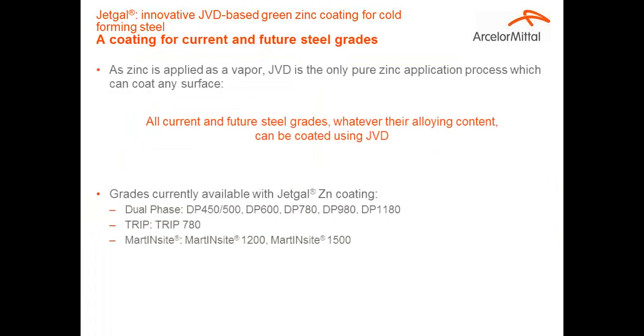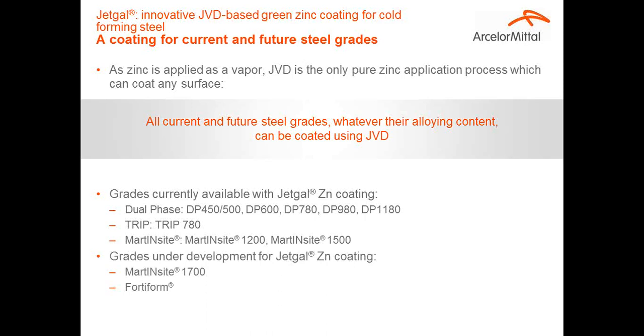So we have decided to use this process for the current HSS and UHSS grades, the ones more sensitive to hydrogen content, and for the future grades, the ones under development. The grades currently available with Jetgal coating are all the DPs from DP450 to DP1180, the TRIP 780, the martensitic grades, martensite 1200 and 1500, and all the future grades in development, such as Fortiform grades and martensite 1700.